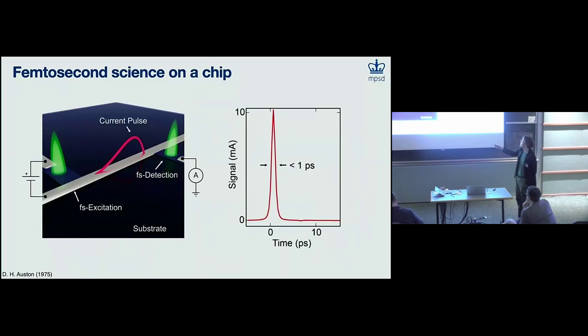And when this current pulse arrives at this second photoconductive switch here, the voltage profile of this pulse, that is the electric field part of the pulse, transiently voltage biases this switch. And if you photoexcite this switch at just the right moment in time, you can sample the current flowing in your signal line. And then by adjusting the time delay between the generation and the detection laser pulses triggering these switches, you can map out both the amplitude and the temporal dynamics of these ultra-fast current pulses on your chip.